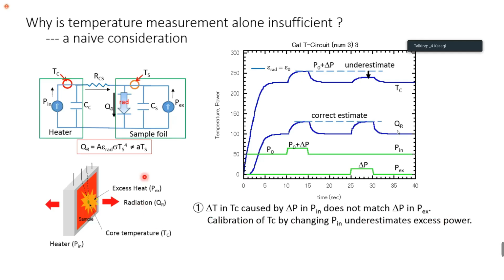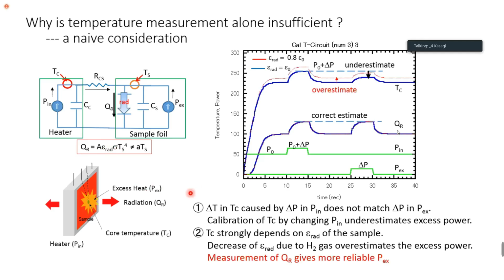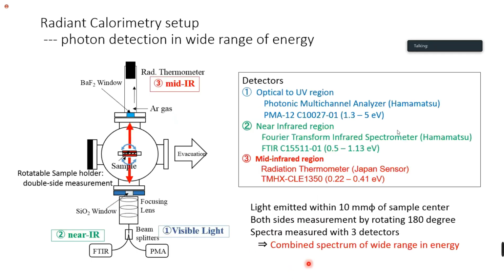Another problem we are thinking about is a change of emissivity of the material. So I changed the emissivity and did the calculation again. The result is this red line. If the red line corresponds to an emissivity 80% of the blue line, then the result is this curve. It's always overestimated. So the core temperature strongly depends on the emissivity of the sample. A decrease of emissivity due to, for example, hydrogen gas overestimates the excess power. Of course, measurement of radiation itself gives more reliable excess heat.